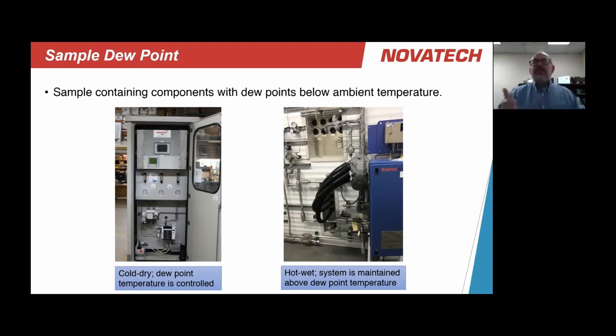Some of the things to keep in mind: sample dew point. We talked about it earlier. And the approaches when we're talking about extractive analyzers are basically two. We can either control the dew point and say, I'm going to change the dew point of the gas by chilling it or using some kind of dryer system so that when it goes into my analyzer, there is no risk of condensation occurring. So my sample might be coming out of a process with a dew point temperature of 70 degrees C. I bring it into my sample system, I chill it so that I drop out moisture, and now my dew point temperature is roughly 4 degrees C. And it goes into the analyzer with no risk of condensation occurring in the analyzer.